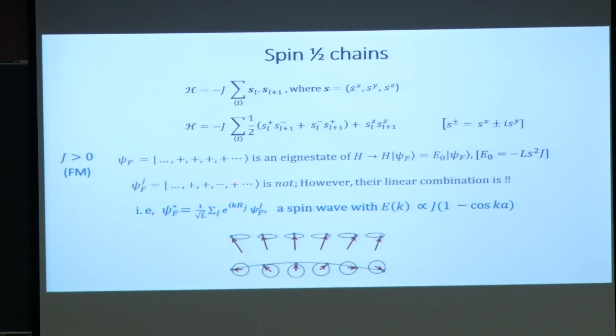On the other hand, if you look at the excitation, so if you flip a spin at one of the sites, let us say the jth site, then you would see that this is not an eigenstate of this Hamiltonian. Which means that if you act with H on this, you wouldn't get this back. However, if you prepare a linear superposition of this, which is written over here, that happens to be an eigenfunction of this Hamiltonian, and this is basically a way to say that your system will have a ground state at t equal to 0 where all the spins are pointing up, and then at any finite temperature you will have spin waves induced in your system. So these are the usual spin waves that you would see in a 3-dimensional magnet.